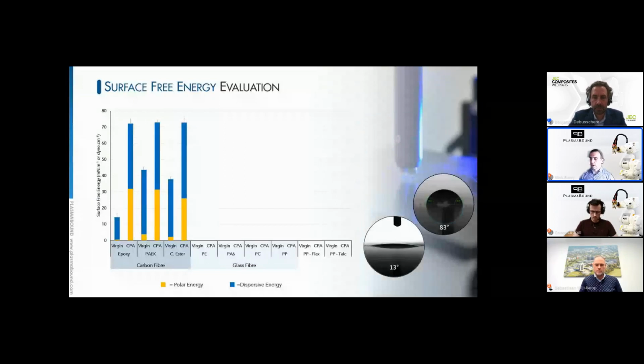So the CPA can remove material, but to further demonstrate its versatility on a range of fibers and polymer removal cases, this chart shows the virgin and CPA prepared SFE or surface free energy values before and after treatment. So again, note we went with polar as yellow and dispersive as blue earlier on. We're going to maintain that throughout this presentation. So firstly, we look at carbon fiber based FRPs. Before, we can see a dispersive surface with a little bit of polar, after a considerable increase in the polar contribution, but also in the dispersive contribution, maximizing that surface free energy up to the limit that is determinable with a water-based goniometry system, which I won't dive into in detail.